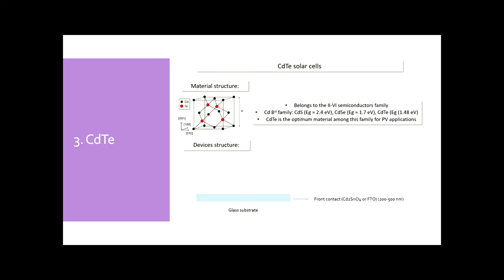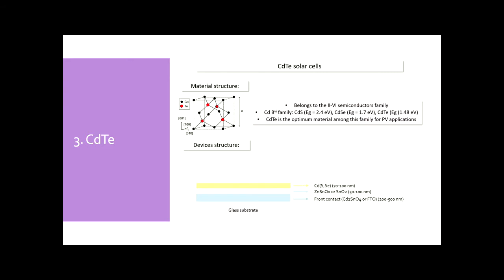Then to build, once again, or here in more detail, a cadmium telluride solar cell, you start with your glass substrate. This is a very special glass substrate, iron free, because it has to be very transparent in that case. Then you deposit a front contact, where the two standard ones are cadmium tin oxide or FTO. This is the thickness range that you can find in the literature. Then you passivate, including a second layer that is zinc tin oxide or tin oxide normally. And then the N-type partner of cadmium telluride.